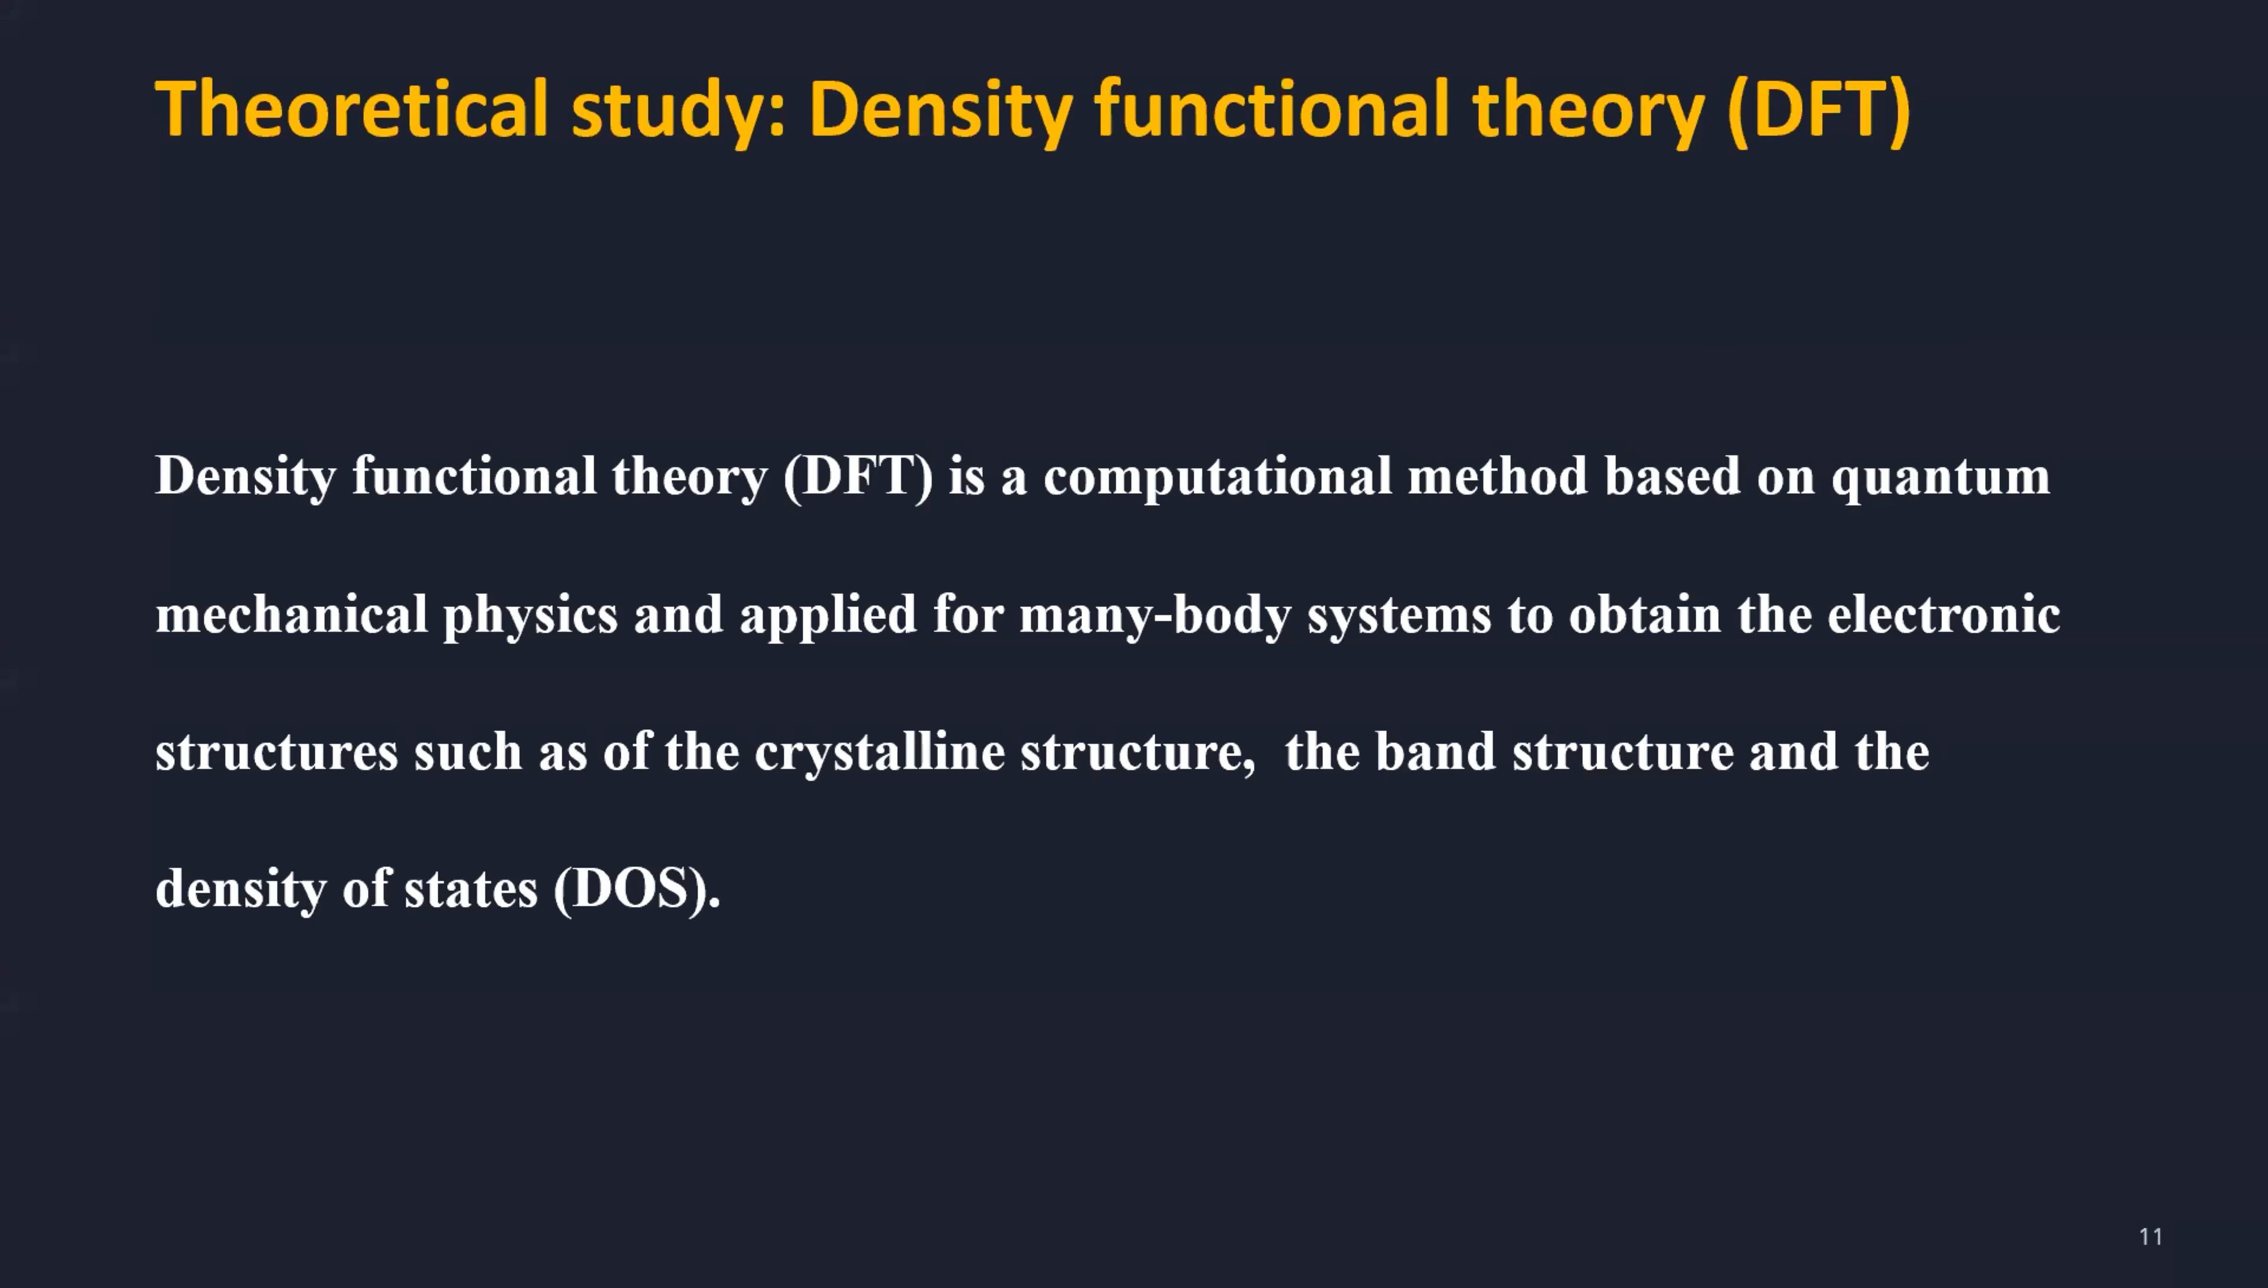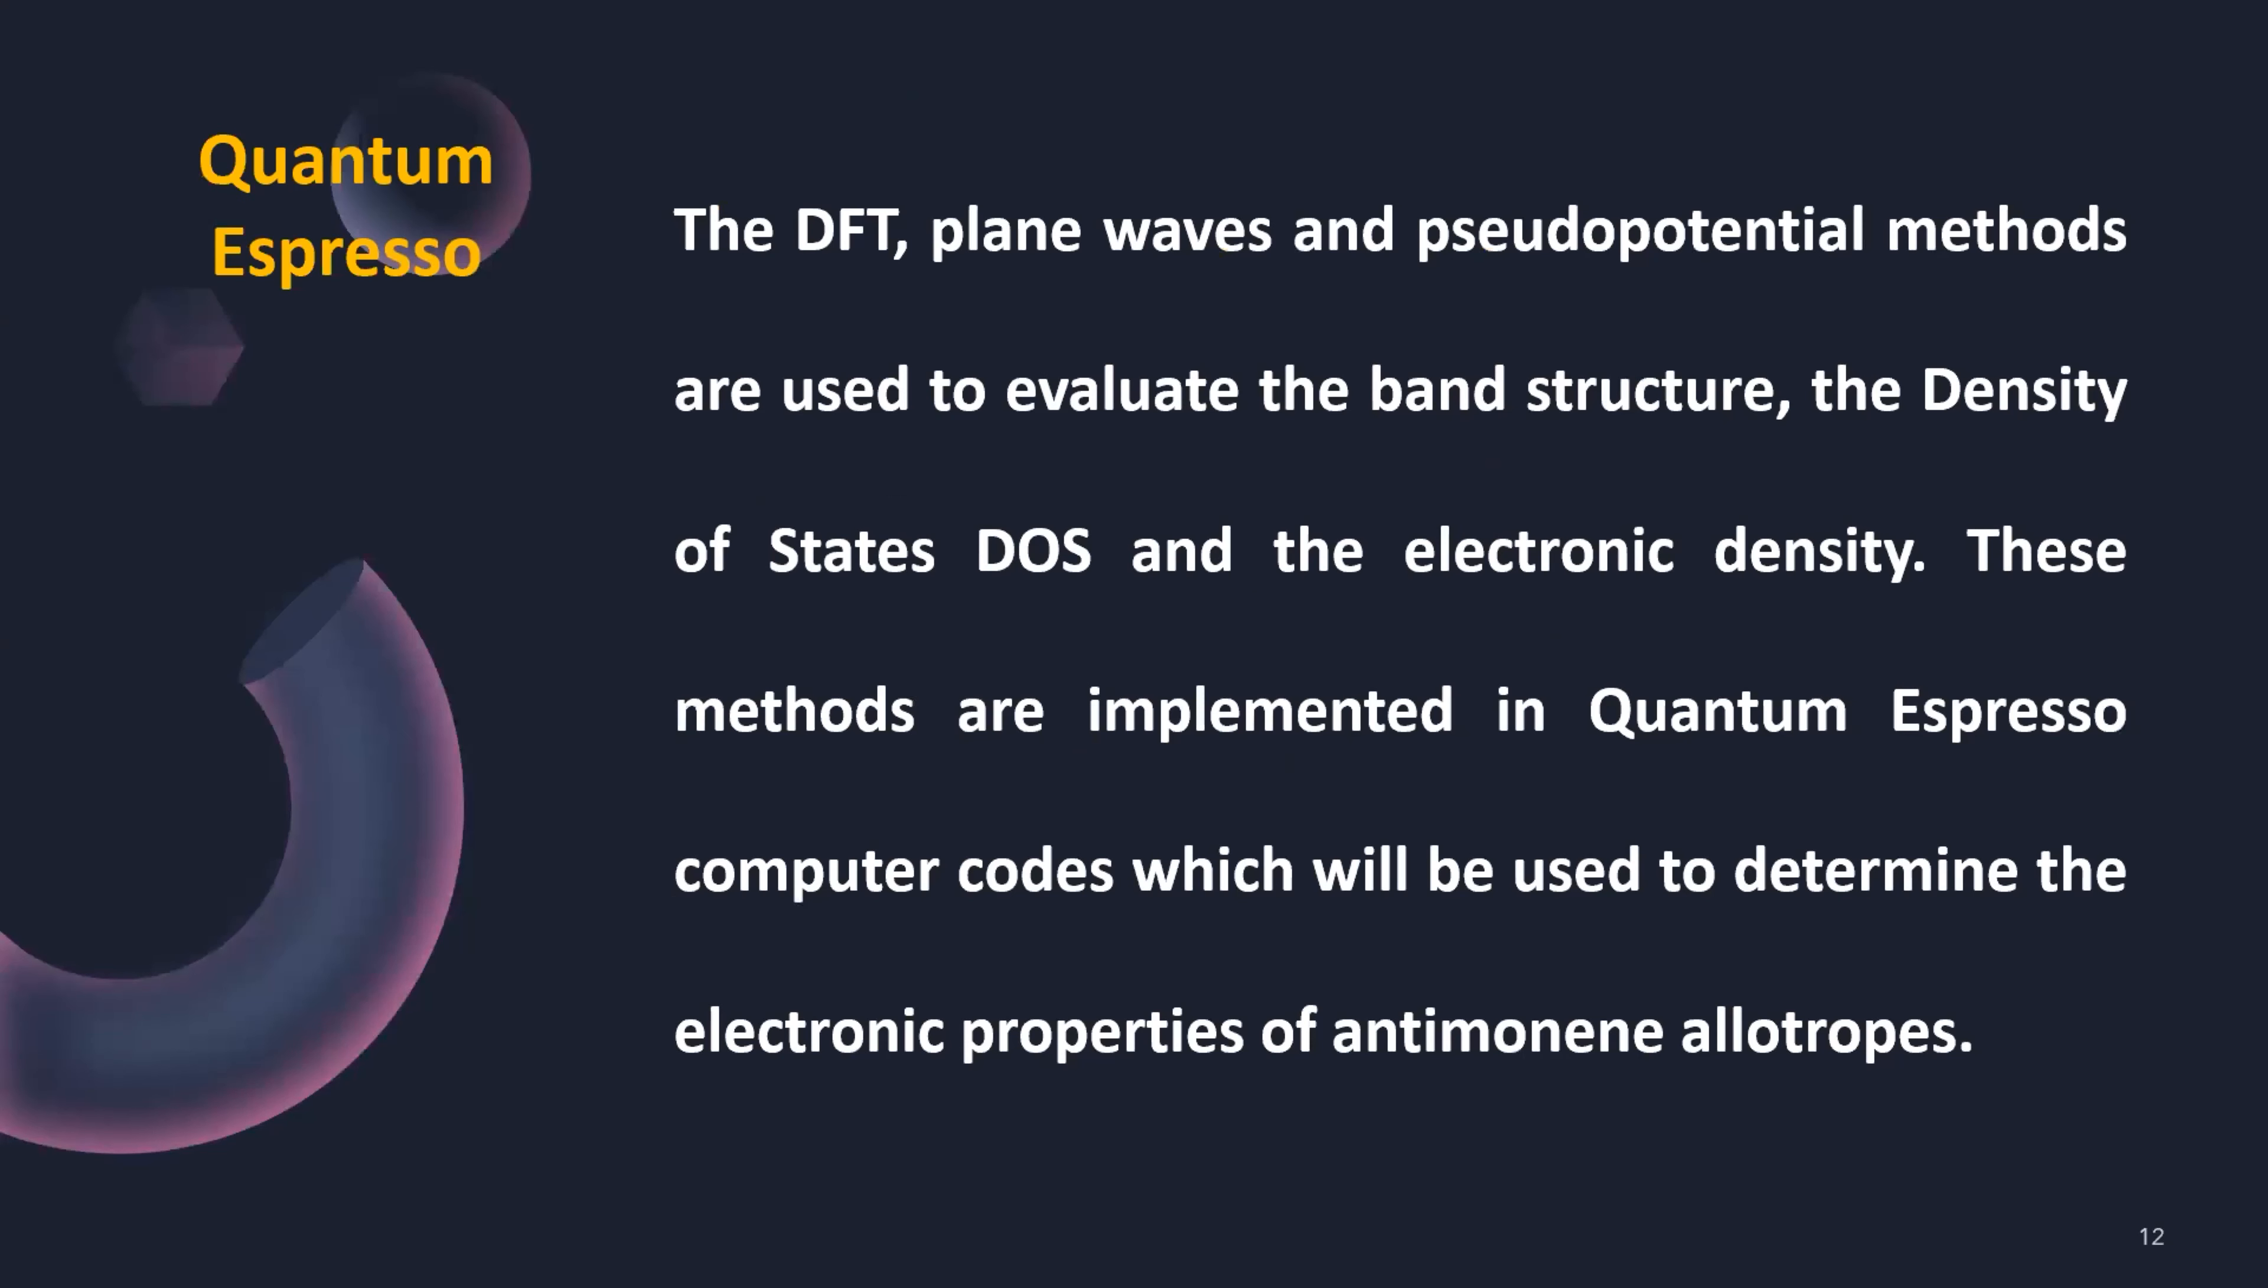The theoretical study of these materials is conducted by using density functional theory, which allows to determine crystalline structure, band structure, and density of states of many body systems. The DFT method is implemented in quantum espresso computer codes. This code is free.